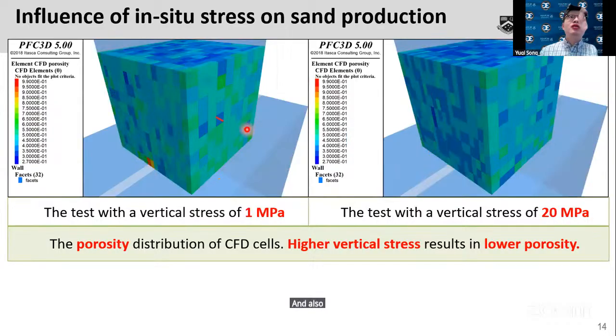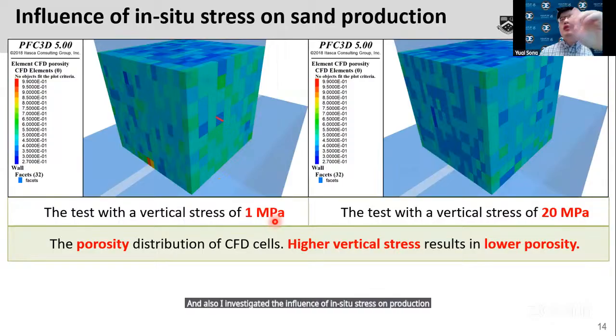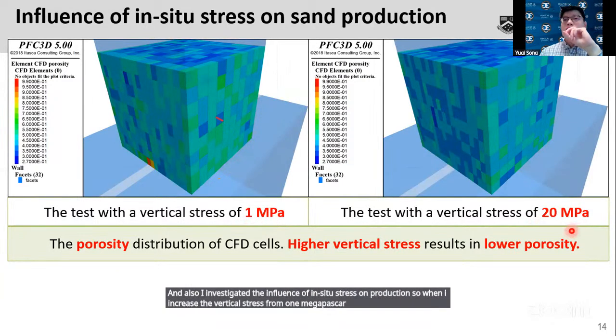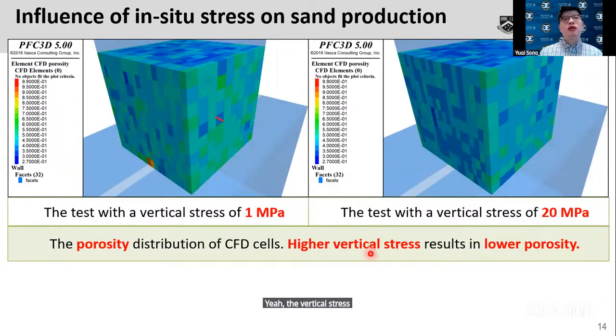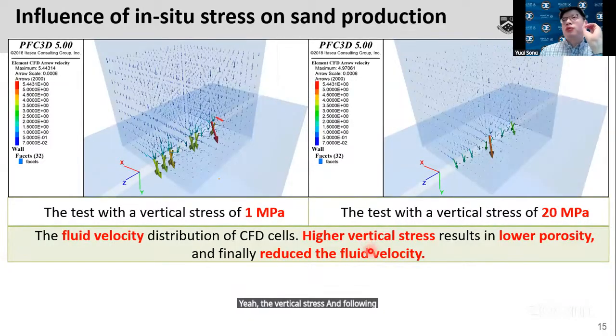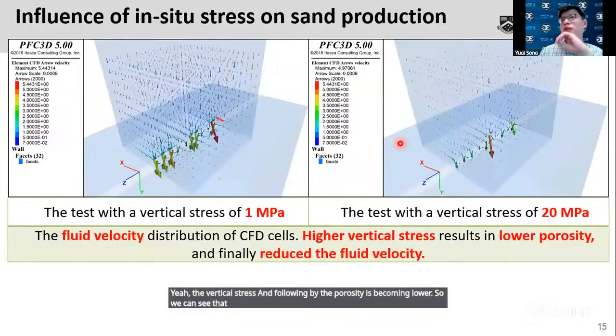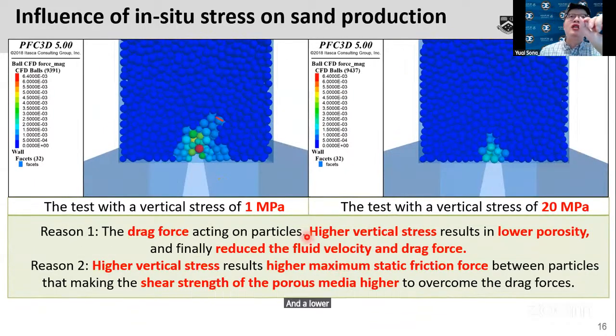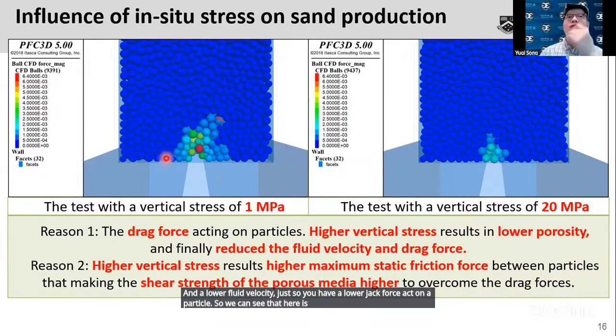I also investigated the influence of in-situ stress on sand production. When I increased the vertical stress from 1 megapascal to 20 megapascals, we first see that the porosity distribution of the reservoir becomes lower as we increase the vertical stress. As the porosity becomes lower, the fluid velocity becomes lower too. So a high vertical stress results in low porosity and finally reduces the fluid velocity. Lower fluid velocity means a lower drag force acting on a particle. Here a larger area has a drag force like this, but in the right figure it's a smaller area.